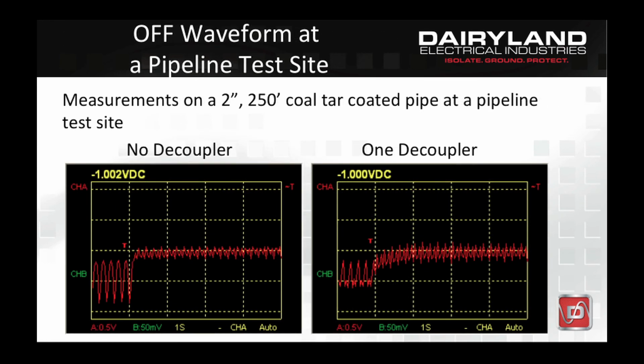This is an example of an off waveform on an extremely short, small diameter pipe at a pipeline test site where an off waveform was recorded with and without one decoupler installed. When decoupled, it took about 1 second or 1,000 milliseconds for the pipeline to reach a stable off voltage. In this case, an accurate off reading could be taken with about a 1 second measuring delay time.